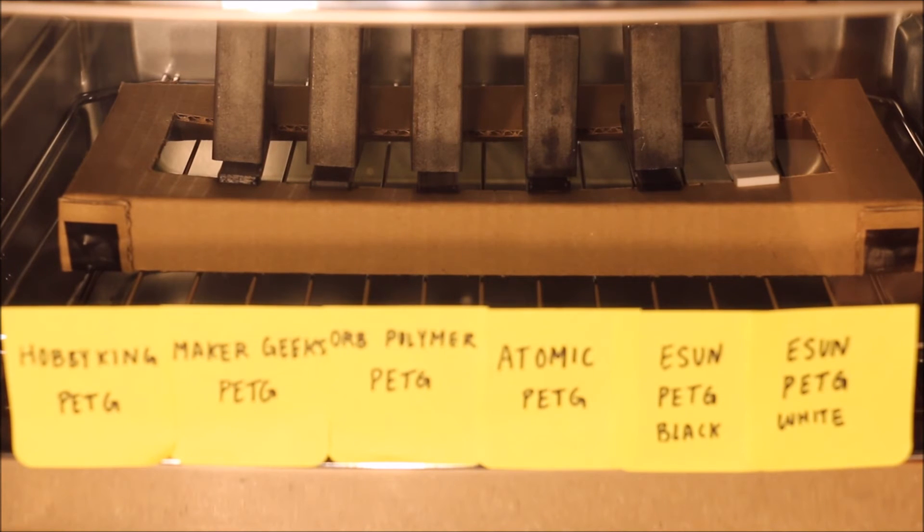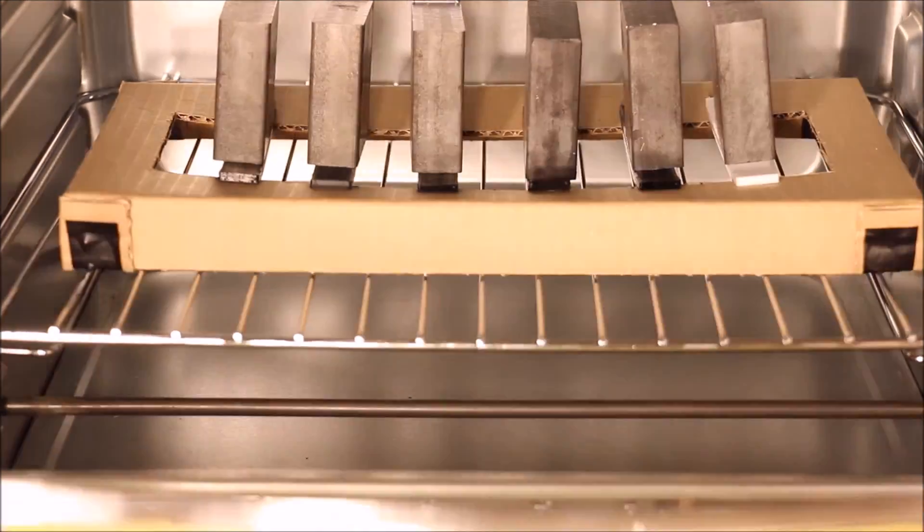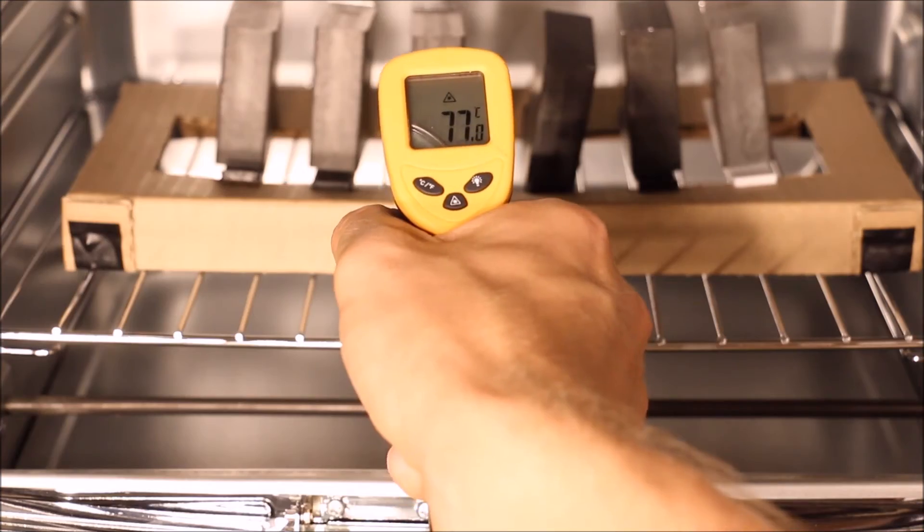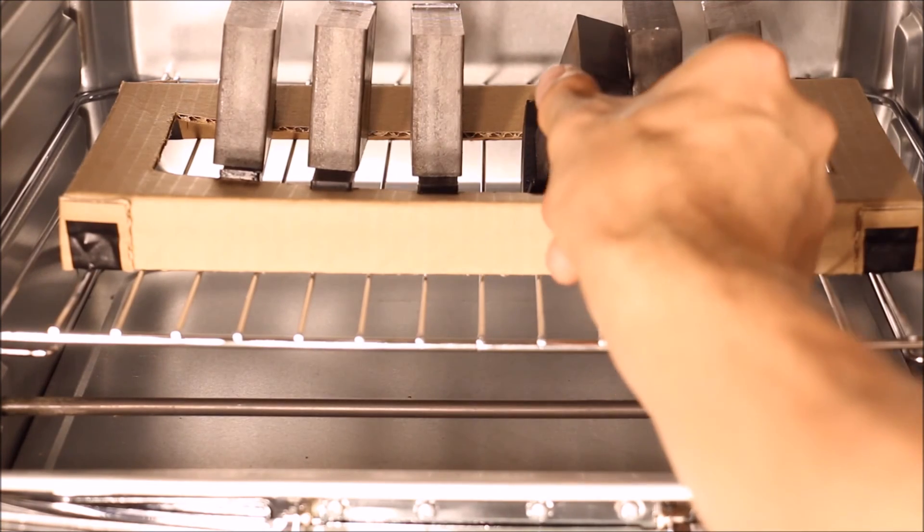It looks like the Atomic PETG and maybe some others are starting to warp. It's about at 75 degrees C. And the Atomic was the first to fail.